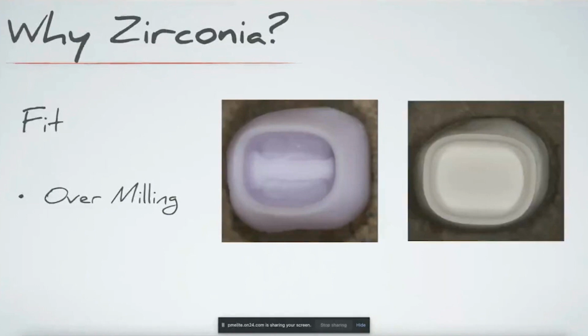And what you see, those kind of ditches that have been formed on the intaglio surface of the Emax, comes from the fact that the diamond burrs that are used to mill Emax restorations have a specific diameter. And so if you have a custom abutment or if you have a prep tooth that has some sharp line angles that weren't rounded over, then the only way that that material can be milled so that it will then seat is for it to be over milled. Now the margins don't have any slop. The margins are actually really clean if you look at them and fit very well. But at the intaglio, there is a little bit of gap there, and that's going to be filled in by resin most of the time, but it will provide probably a little bit different of an intimate fit than what you're going to find with the restoration on the right.